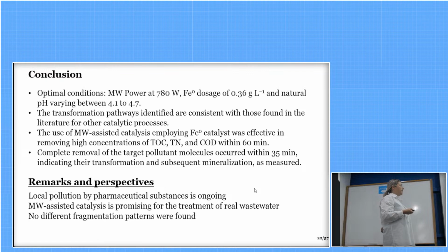The use of microwave-assisted catalysis using zero-valent iron as catalyst is effective for removing the high concentrations of total organic carbon, total nitrogen, and chemical oxygen demand within 60 minutes. And the complete removal of the target pollutant molecules in the study, ibuprofen and diclofenac, occurred within 35 minutes. So our remarks in this study and perspectives are that the local pollution by pharmaceutical substances is indeed ongoing. The microwave-assisted catalysis is promising for the treatment of real wastewater, and no different fragmentation patterns were found. So this process does not increase the toxicity of the final effluent.